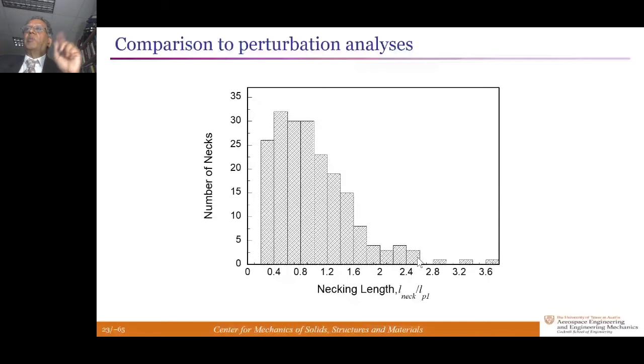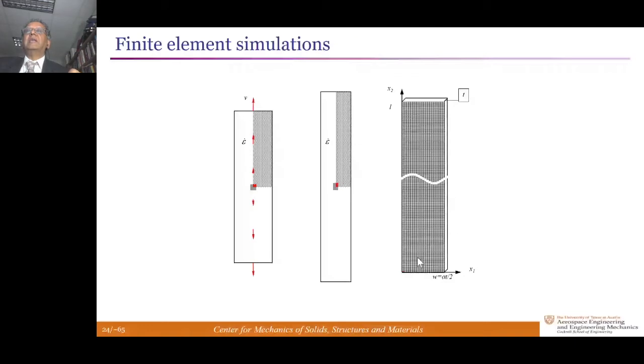I think it's more appropriate to think of a point perturbation and see how the point perturbation will propagate through the cross-section of the specimen. And we attempted this through a very simple numerical analysis. Take our specimen, do a 1/4 symmetry model of that, put a defect at one corner, and see how the defect propagates across the cross-section.